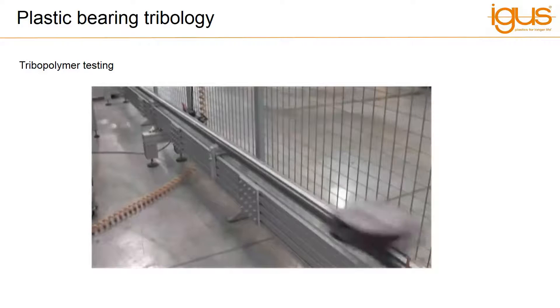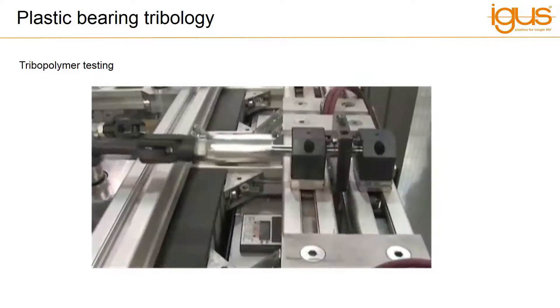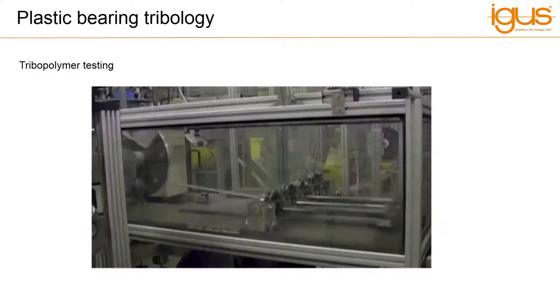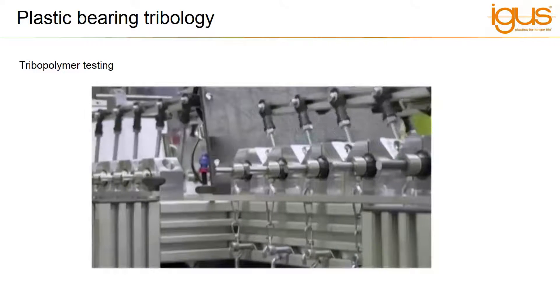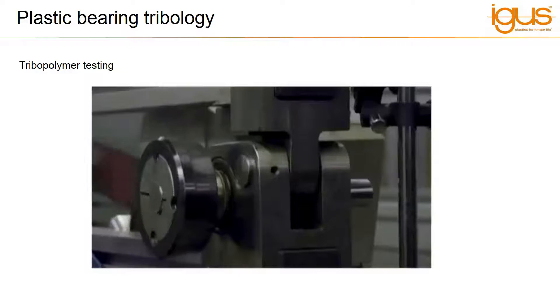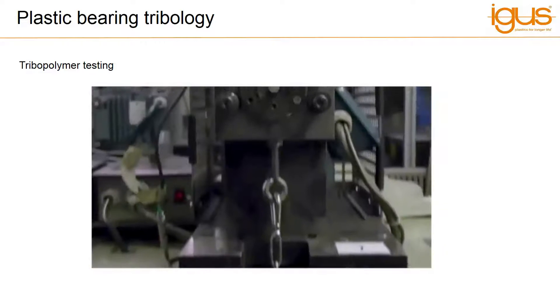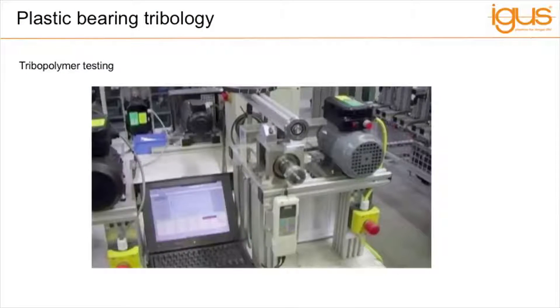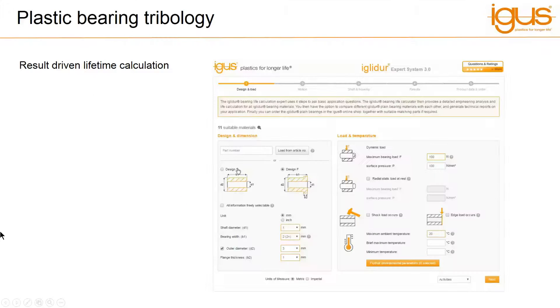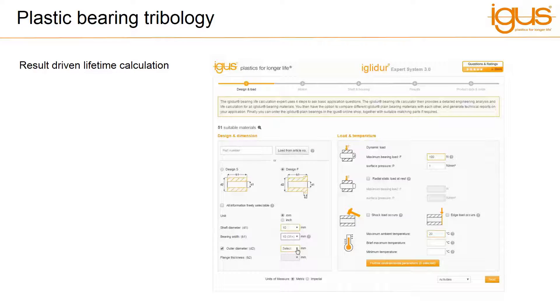This has proven essential for confidence in tribopolymers to grow to a new level, especially when considering the 1,000-plus customer-specific tests we carry out each year. This short video demonstrates the diversity of requirements to ensure the reliability of tribopolymers: tests under oscillation, rotation, extreme loads, extreme speed — both in linear and reciprocating movement — on small diameter bearings from one millimetre up to high load, slow movement on very large diameter components. Due to the predictable nature of tribopolymers and the results of thousands of hours of test data, we can predict the lifetime of an IGLIDUR material, which is linear if environmental parameters remain the same. An application with constant speed and forces will exhibit a wear pattern represented by a straight line graph.